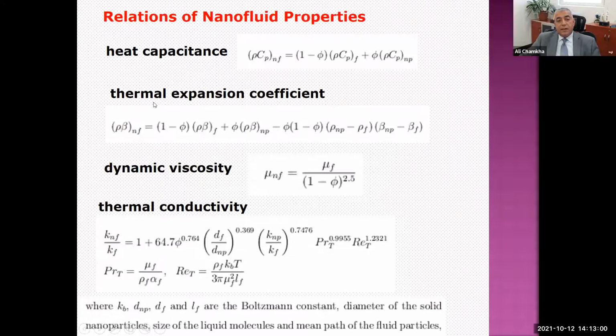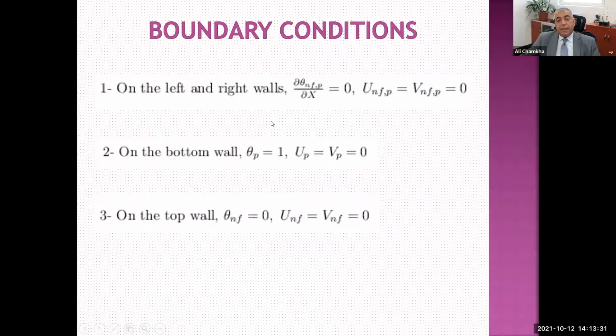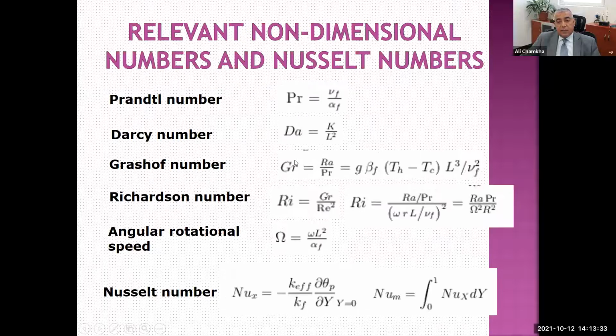Of course, here you see the properties of the nanofluid. And the most important here is that we're using a totally different model for the thermal conductivity of the nanofluid, which depends on the Boltzmann constant, the diameter of the solid nanoparticle d_np, the diameter of the liquid molecule d_f, and l_f, the mean free path for the fluid particle. This model is in the literature, we used it, and then we go to the results.